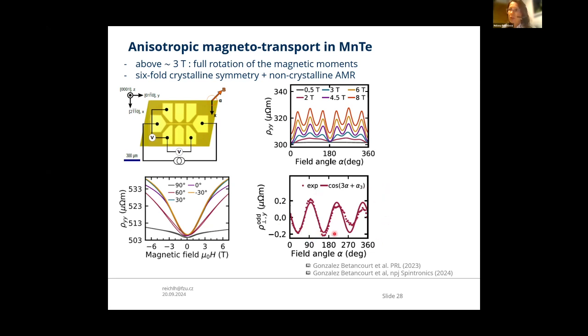in the transversal contacts simply. Some people would call it planar Hall effect, but let's just call it transversal signal here. And here we see that in our case, the transversal response is not only the cosine-like contribution, which we would expect, but also a threefold symmetry. And this threefold symmetry again is yet another evidence that the anomalous Hall effect which we observe is indeed of altermagnetic origin, and it's also present in this angular dependent magnetotransport.